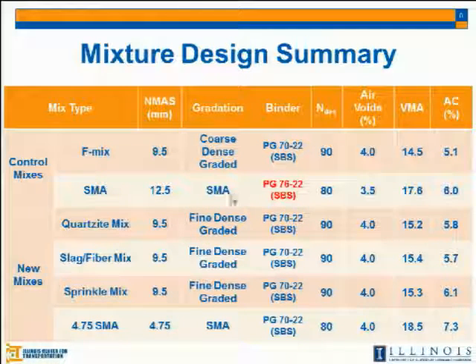To have the compactability and thinner layer, we designed the aggregate gradation to be the fine dense gradation by using the Bailey method. We used the PG 70-22 for all of the mixtures except 12.5 SMA. We cannot control this too, because this is commonly used in Illinois. So we just sampled these two materials from the plant.